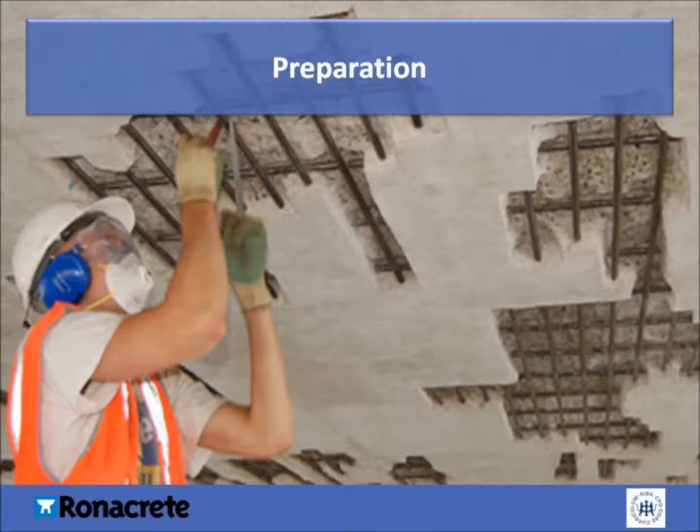As with many concrete repair projects, the key to a successful outcome is in the preparation. Key techniques include removal of algae, usually with a proprietary algae remover. Grit blasting of the concrete surface and reinforcing steel. However, this may not be necessary when using polymer mortars. Needle gunning to remove defective concrete. Sawing edges at repair perimeters to avoid feather edging of repair material. Wire brushing of reinforcement if required.